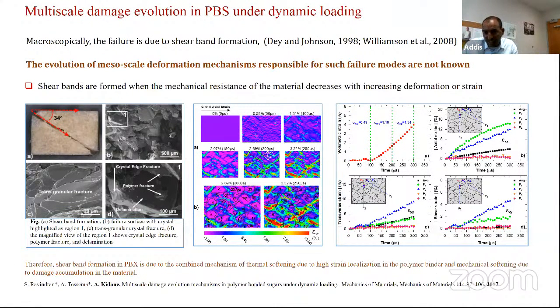So these materials usually fail by shear banding. As we know, shear bands form when the mechanical resistance of the material decreases with increasing deformation. Most metals go to large deformation, but unfortunately, in this material, the shear band happens at low strain, and we're trying to see what causes shear banding. We use this local DIC, which is very small, on the order of 10 microns per pixel, and we are able to measure not only the heterogeneity but also the strain on the specific grains inside these materials.